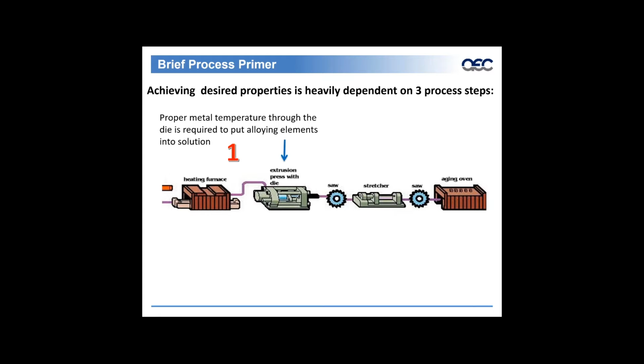So the first stage that's most critical: proper metal temperature through the die is required to put alloying elements into solution. So our raw material that's being supplied to our oven, that's in line with the extrusion press, has already had the homogenization cycle. So at this point, we are trying to achieve our proper billet temperature that is being applied within the extrusion press. So that's a key aspect of it.